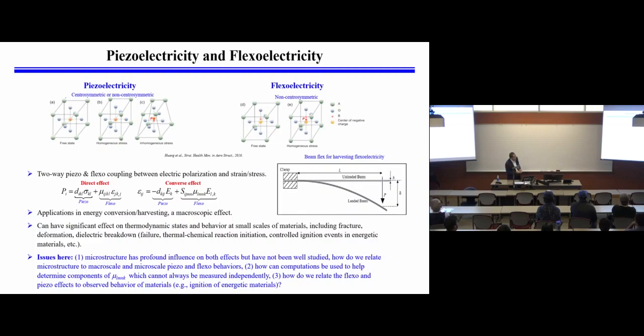The difference is that the flexoelectric tensor that relates the strain gradient and the electric output is a fourth order tensor. And it's very complicated, right? So how do you measure those if it's fully anisotropic? You have 81 constants because you have four components. That's a lot. That's very difficult to do.